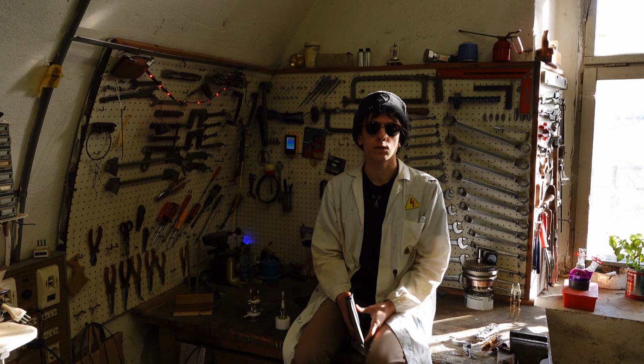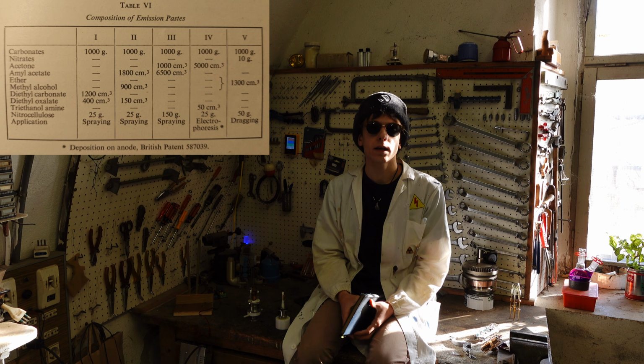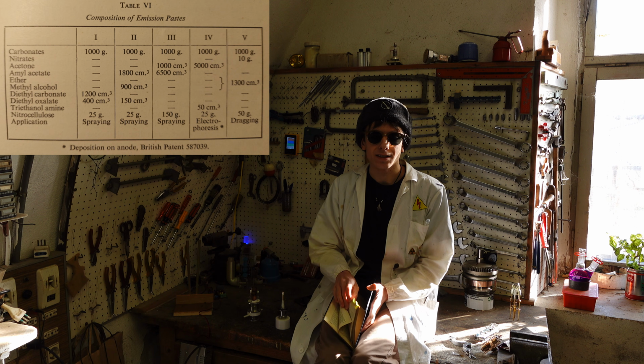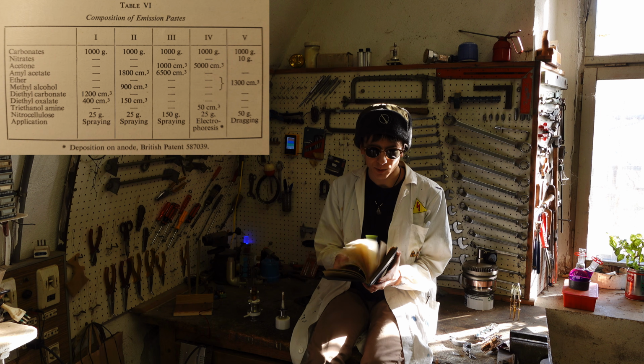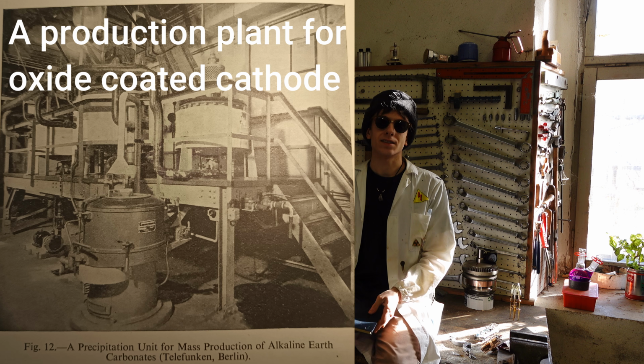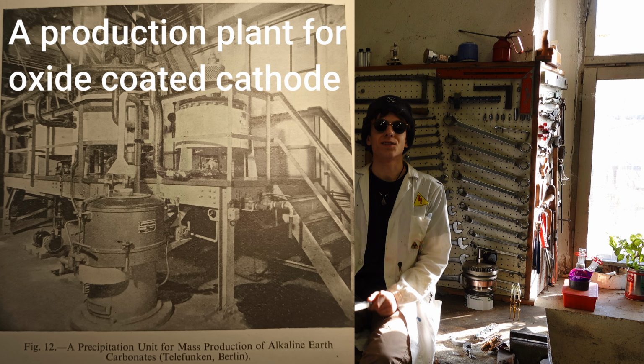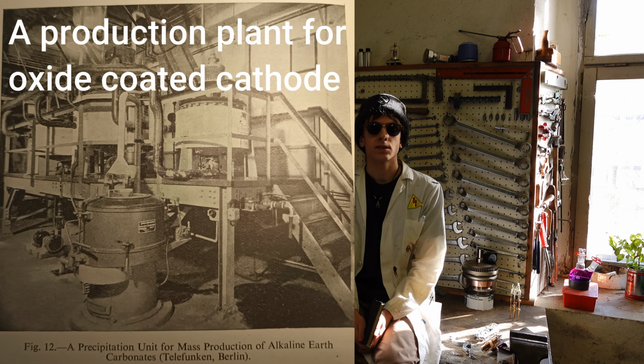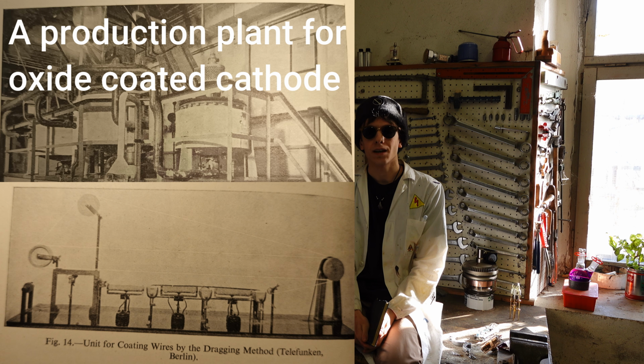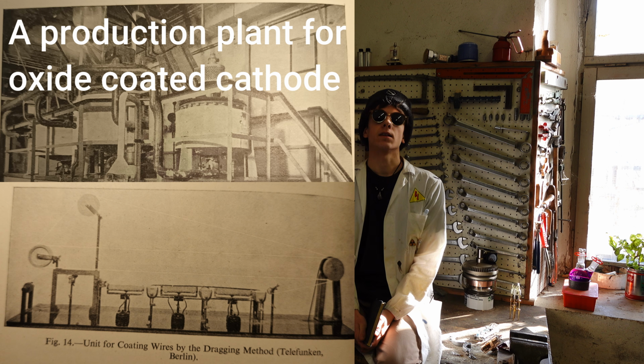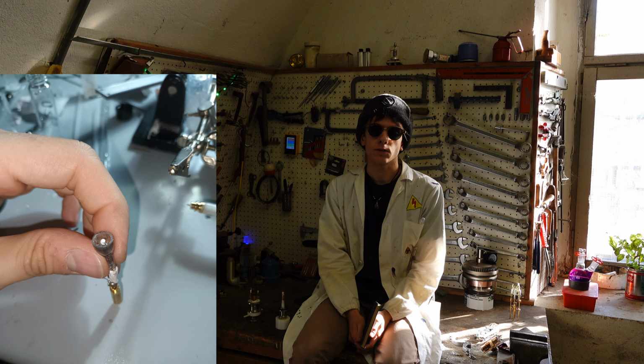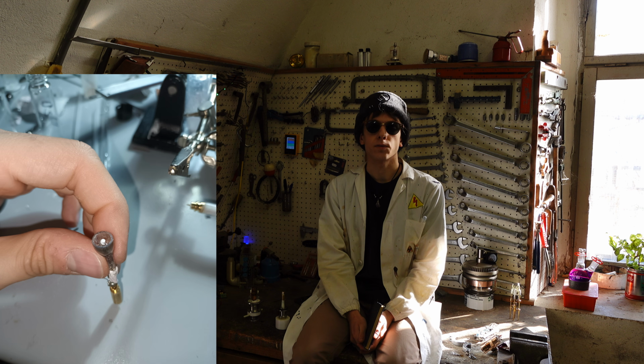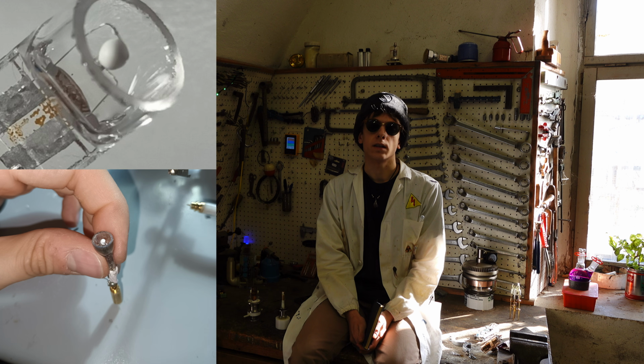I was able to find the secret recipe used in this 1950s book that uses strontium and barium oxide and some other organic activating agent like nitrocellulose. I have yet to give the original carcinogenic formulation a try because I got good results even with my alternative, which consists in making a coating using a water suspension of finely ground strontium carbonate, then dipping it over the filament and letting it dry with gentle heating in air.